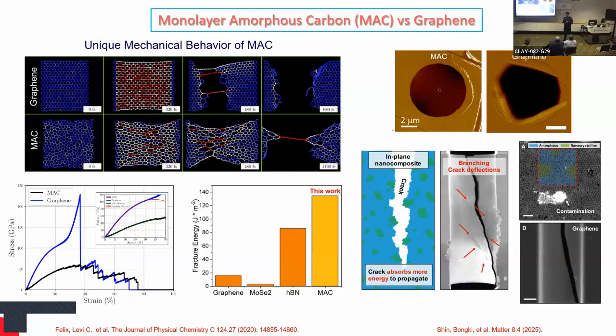You can, yeah, that's possible, but we haven't tried that one, because it likes to come from graphite to graphene, like in terms of vapor exfoliation. But in this case, I don't think it's very difficult to break the bond. So we haven't tried. In general, when you grow by CVD, we always form a lot of amorphous carbon. We tend to avoid that as much as possible. But here you're able to control that growth as a single layer.